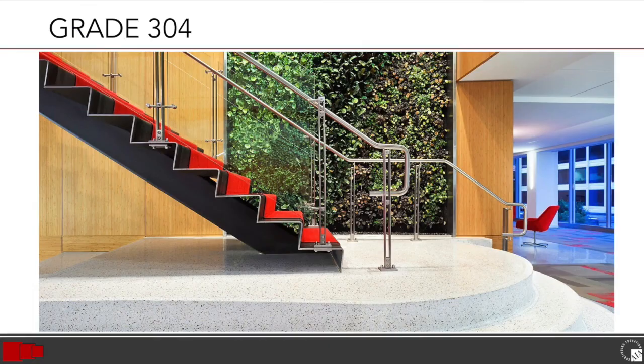Stainless steel 304 grade posts and railings are often used in protected outdoor areas or areas where weather conditions aren't very harsh, and they don't need a protective coating and are usually finished with satin or mirror to protect from corrosion. 304 grade steel railings are also a great choice for indoor railings and need nothing more than regular cleaning with soap and water to maintain. One caution with 304 grade is to beware of installing stainless steel 304 in salty or chlorinated environments, as they will cause corrosion.